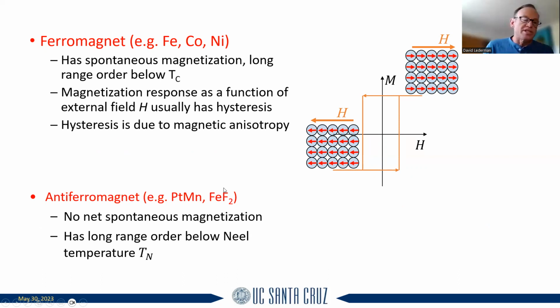Now there are materials that, as I said before, might have an interaction that makes the spins that are somewhat localized around each atom align antiferromagnetically to each other. So that means that, for example, you could have one row of spins that point in this direction, another one that points in this direction. There are different arrangements that you can think of. But the point is that this, in principle, has a very small magnetization. At low temperatures, it's really small as the field goes to 0.